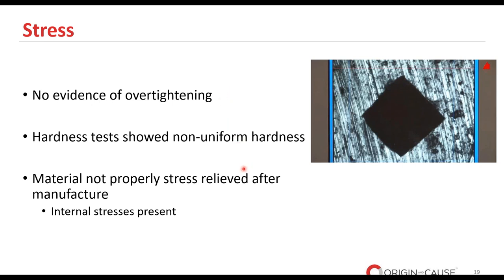And variation in hardness can create differential stress zones, meaning different stresses in different areas of the material, potentially initiating or propagating cracks. So it's more likely that the material wasn't properly stress relieved after it was manufactured. Stress relieving is an essential step to ensure even stress distribution across the part and prevent internal stress concentrations. So what's the conclusion here? Internal stresses were present in the material, and this presents a substantial risk, especially when considering potential for stress corrosion cracking to occur.